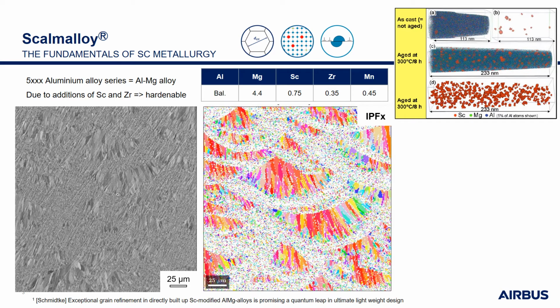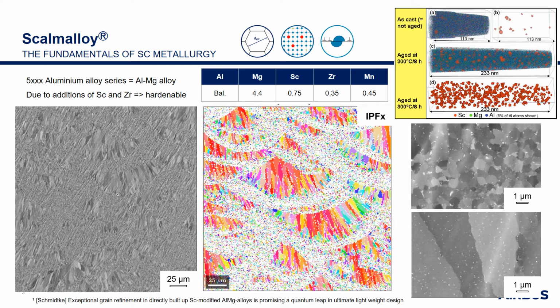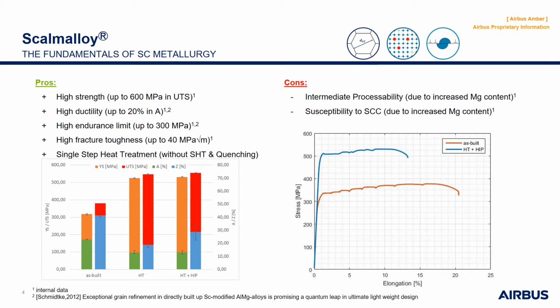This bimodal microstructure, in fact, has a fine-grained area with a grain size way below 1 micrometer and a columnar coarse grain size with approximately 10 micrometers in grain size. The mechanical properties arising from this unique microstructure are quite outstanding for the 5000 alloy series and in fact for most aluminum alloys. So we see a high strength and simultaneously high ductility. We face a high endurance limit, high fracture toughness, and this we obtain after a single step heat treatment without solution heat treatment and subsequent quenching, which in fact is a major advantage for, for example, complex structures.